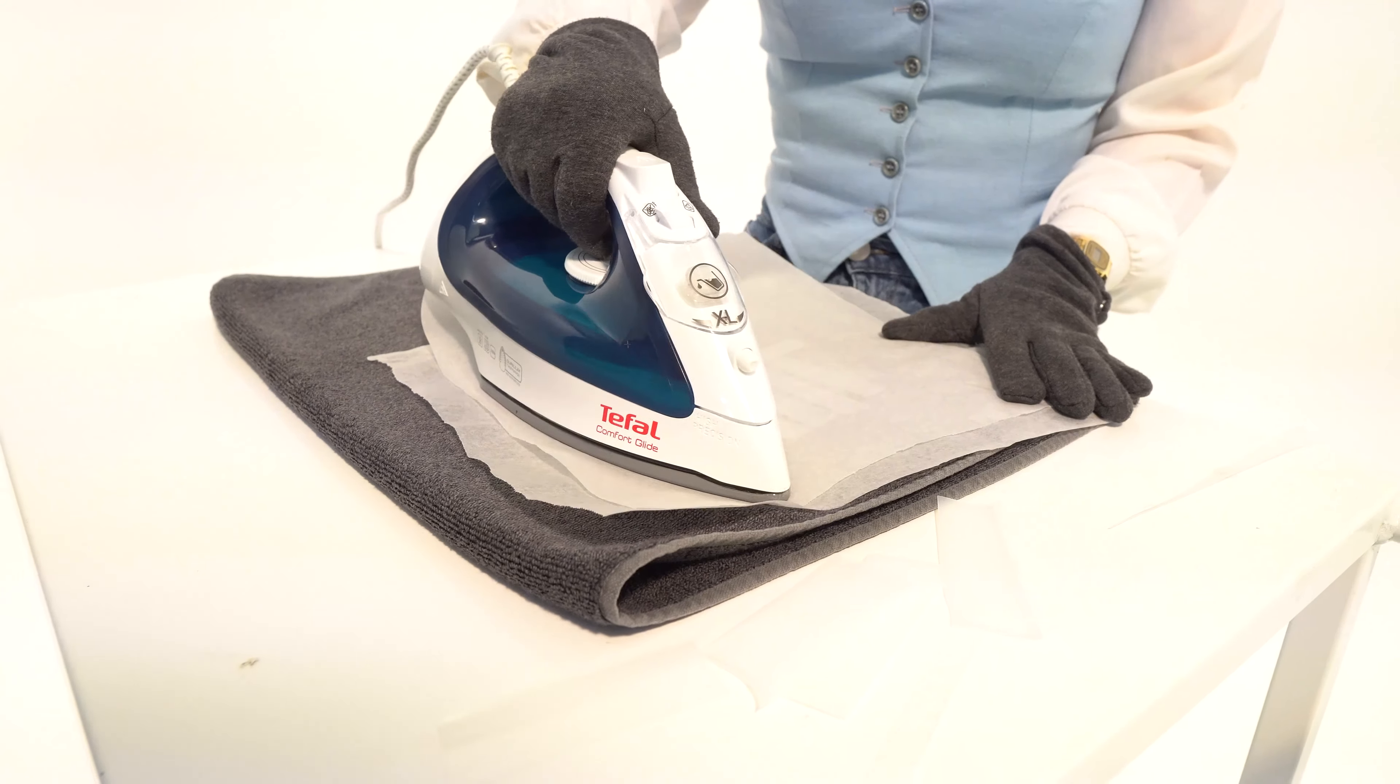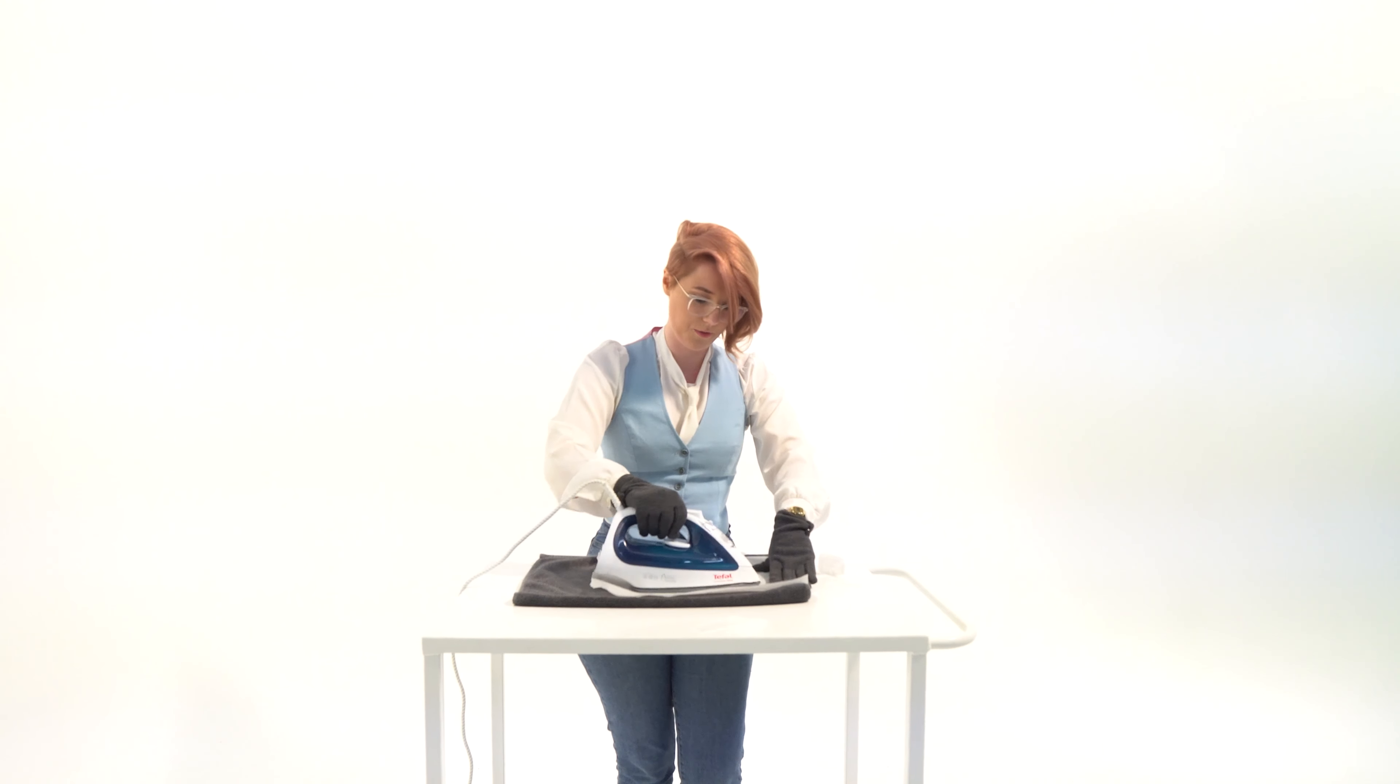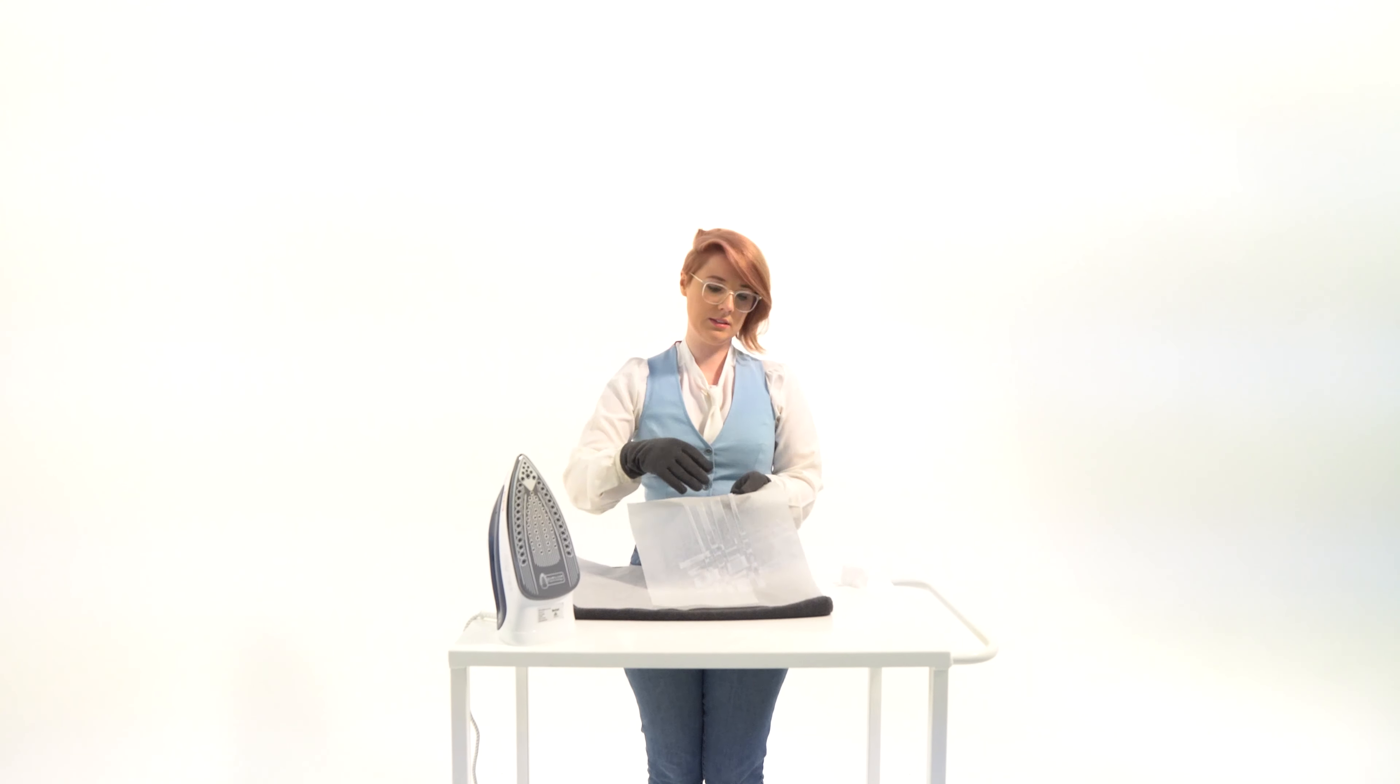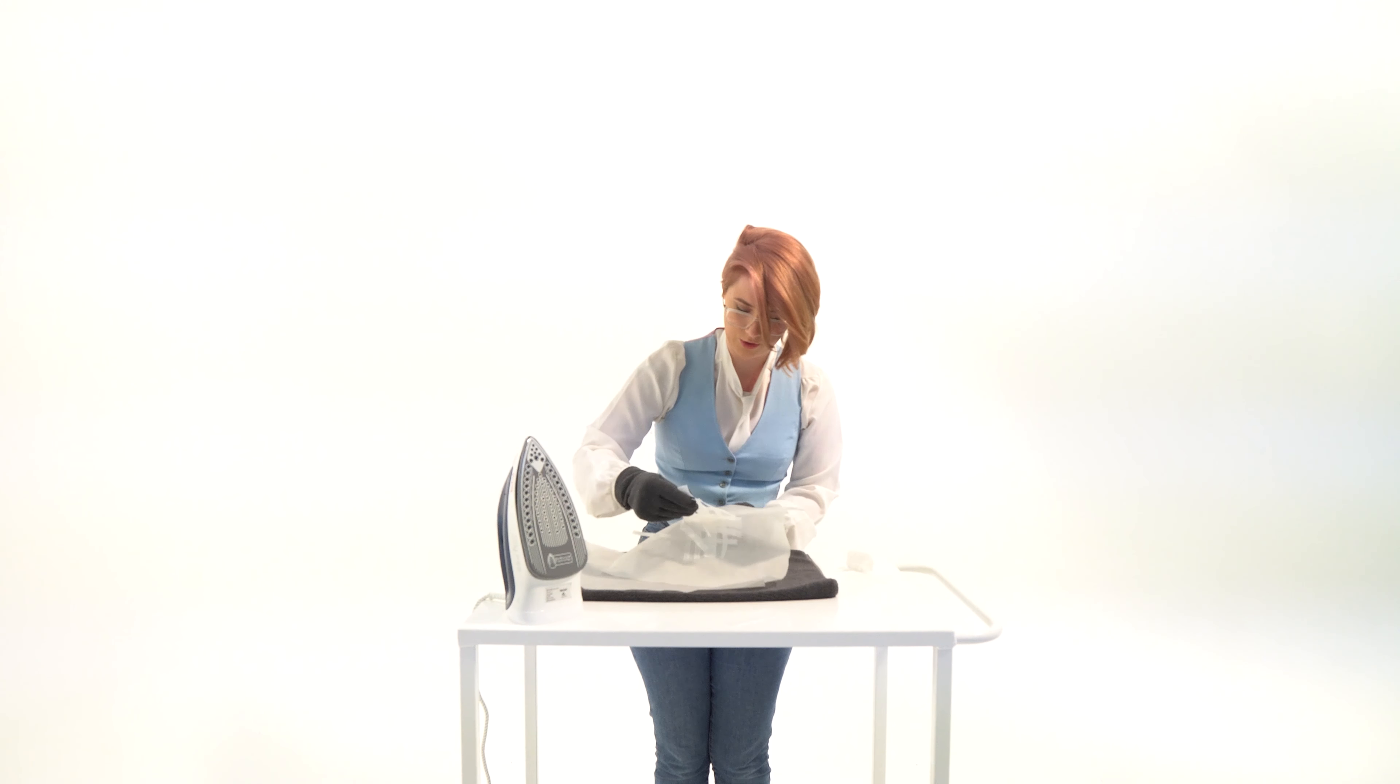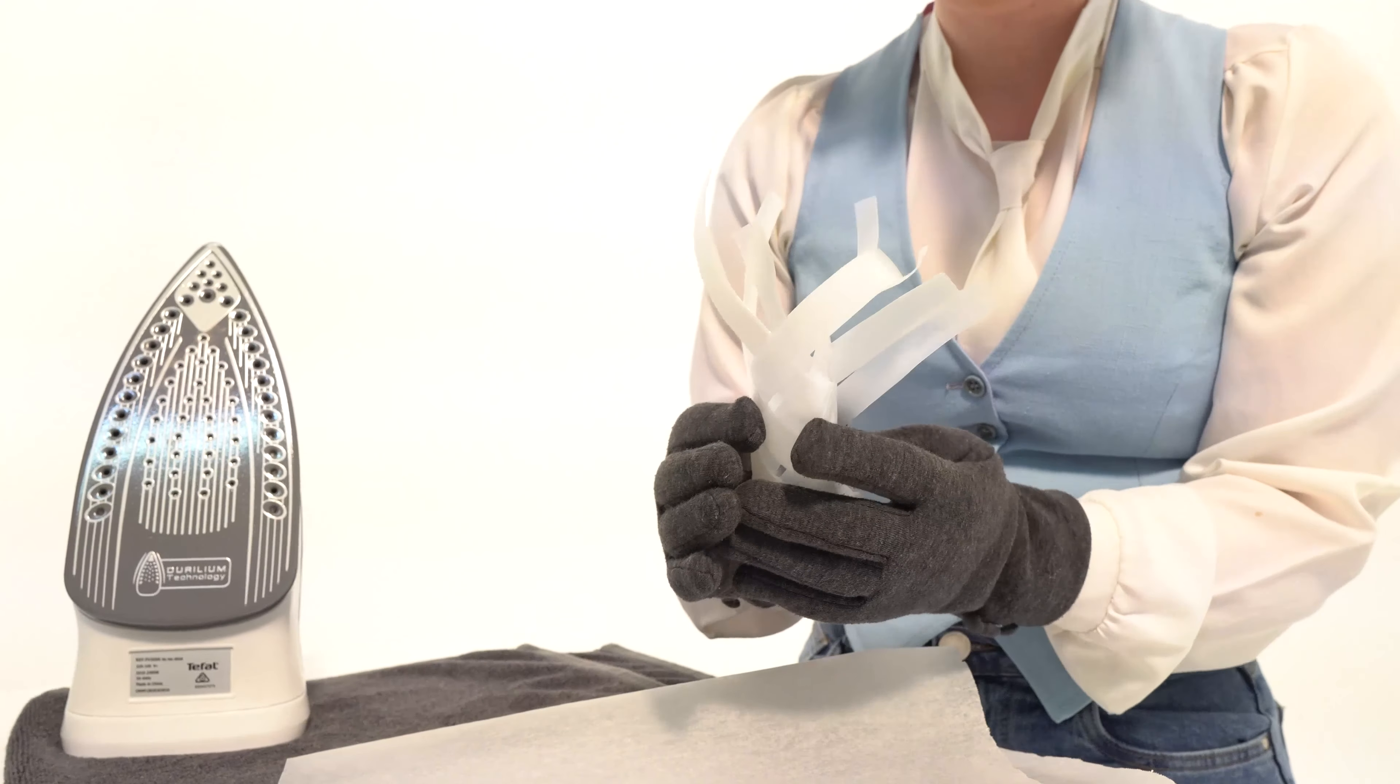This is a bit of a bigger surface, so when you're going across a bigger surface it can take a bit longer to heat up. You'll notice with something like this that certain points of it heat up before others because you've got double layers of plastic, so it can take longer for the heat to actually get through. Then I can open it up and you can see that that's become one piece. As I pull that off, it can sort of slump against each other and stick, so that's where you want to be careful. You might want to wait for it to get a little bit cooler before you get it off, but it also shows you how you can start shaping and reattaching parts if you want even thicker layers to reform. You can fold the plastic round, you can start going on diagonals to get more complex patterns.